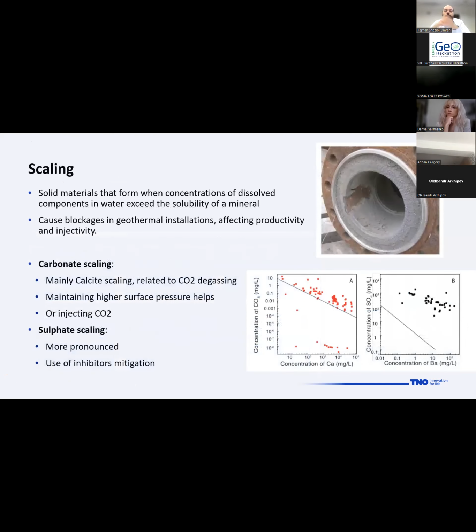The second problem is the scaling. Scaling happens because you have this salty brine with different minerals in it. And at a certain point, because you change the conditions, you make it very favorable for these minerals to come out of the solution. And you have different types of scaling. You have carbonate scaling, you have sulfate scaling. And if you look into all the geothermal systems, here I show the calcite and barite equilibrium at what we call infinite dilution. And in the salty water, you already see that you go way above the saturation line. So the chance of getting this sort of carbonate and sulfate scaling in the system, if the minerals exist, is pretty high.